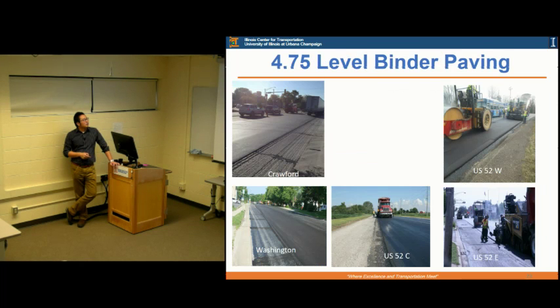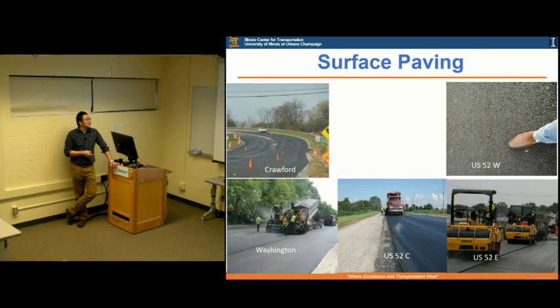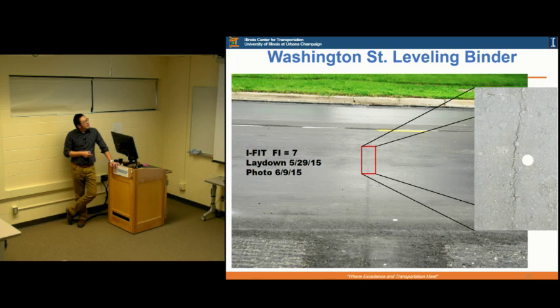So we have some photos from the construction site, and this is for the level binder. As I said, you put the level binder course, and then you put the surface, the overlay. So we did some surveys to see what is going on in the field, if there's any cracking or distresses developed. This is showing that just after less than one month, you see cracking develop, which is reflective cracking.